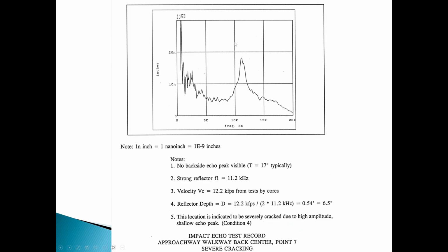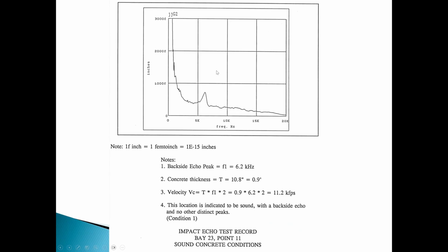So this was an example of a higher frequency echo that 1 over 6,200 hertz is the echo time, and 1 over 11,200 hertz is the time for that compressional wave to go back and forth. But it's resonantly echoing it multiple times, and that's what we pick up.